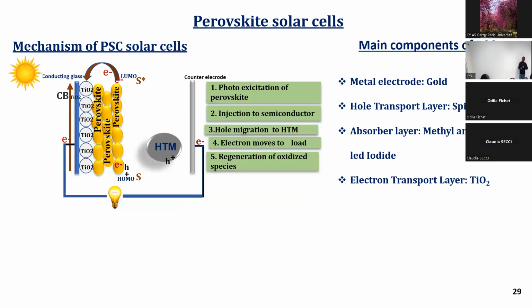Mainly, the components of the perovskite solar cell are: the metal electrode, using gold; the hole transport material, usually spiro-OMeTAD; the absorber layer, methylammonium lead iodide; and the electron transport layer, here TiO2.